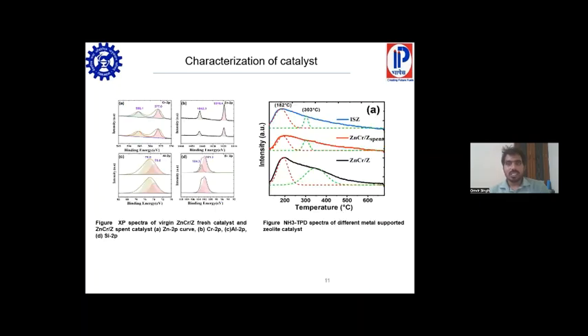Then come to XPS to know the oxidation state of the material. Chromium shows two spin components. The first spin component is at 586.1 electron volt, that is 2p1/2, and the second spin component is at 577.0 electron volt, which is due to 2p3/2, which can indicate chromium in +3 oxidation state. Zinc shows two spin components, first at 1042.3 electron volt, that is 2p1/2, and second at 1019.4 electron volt, which corresponds to zinc in +2 oxidation state.